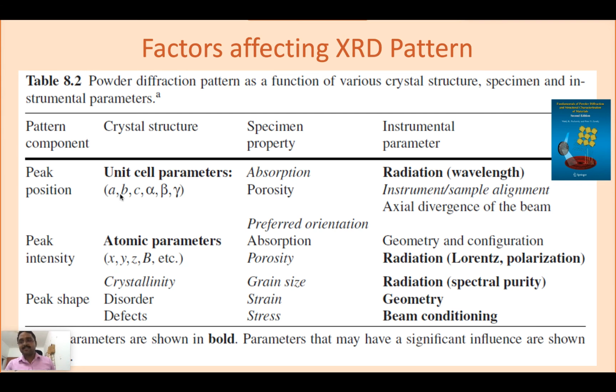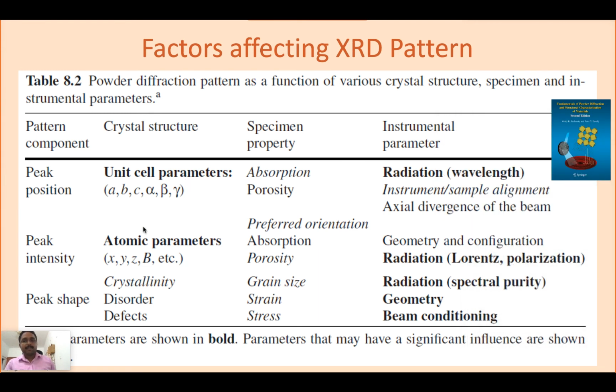So peak position is always determined by a, b, c, that is the unit cell. Then peak intensity is determined by what type of atom is present. A very good guess here. Why? Because if the atom size is bigger, what will happen? More electrons are there, more possibility of diffraction will take place. So elements lighter than oxygen we cannot detect using X-ray diffraction, because the diffraction strength is not there. In that way, the x, y, z position parameters will give you the peak intensity.